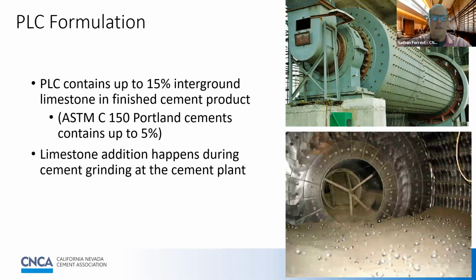This is a ball mill, and it's the final step in manufacturing Portland cement or Portland limestone cement. The difference is the amount of limestone that's introduced during this step. Portland cements under ASTM C150 are allowed to contain up to 5% limestone, whereas Portland limestone cements under ASTM C595 are allowed to contain up to 15% limestone. By doing this at the cement plant in the ball mill, we're able to produce a homogeneous material that's closely interground and performs very well.